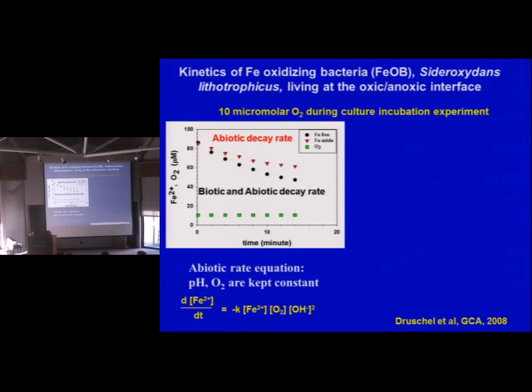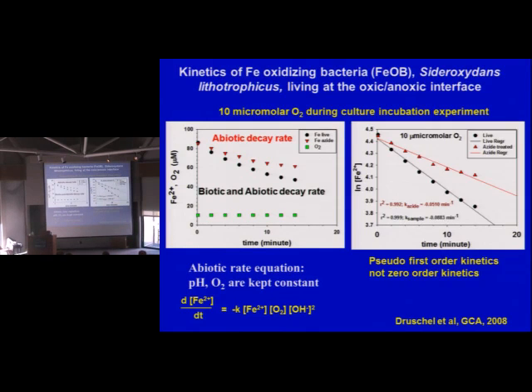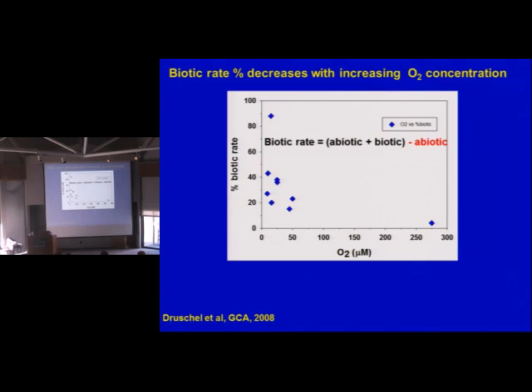All right? Now, if I do pseudo first-order plots, what you'll see here for the red, which is the azide killed, you notice that the rate constant for the decay is about 60% of what the rate constant is for the abiotic and biotic. So you can see that this is much faster when the organisms are present right there. Okay, so we can now discriminate those. And we can now say what's the percentage of oxidation due to abiotic and what's the percentage of oxidation due to biotic. So this is what Greg came up with.